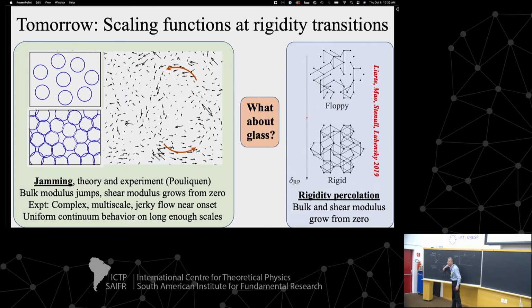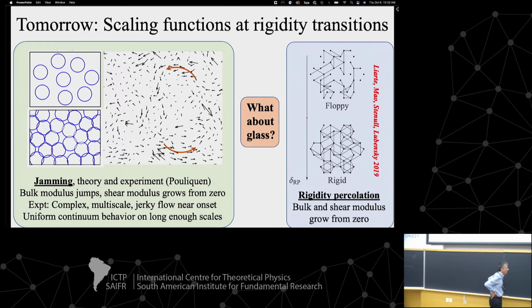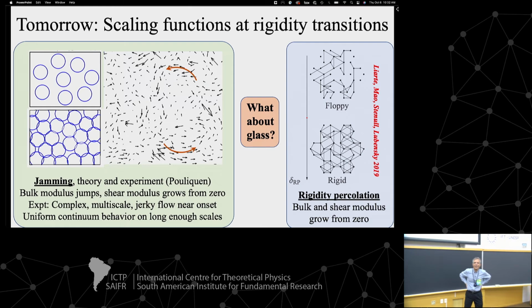lots of phonons here. And if you had a density of states that was constant all the way to the jamming point, this boson peak would get to lower and lower frequencies. So I'm not actually sure, I'm sure somebody's done the calculation in this room, whether this becomes a power law, whether at the jamming point you violate some thermodynamic bounds, I don't know. You can't have too much specific heat at low temperatures because then the entropy can go to minus infinity, never mind. Anyway, it's a classical system.